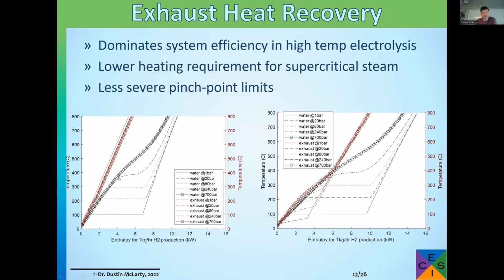The supply water is in the black lines, and the return exhaust gas is the red, at different pressures. And you can see as you go to higher and higher pressure, you get to supercritical steam, you actually need less heat addition. So this difference at the top between the red exhaust and the black supply, that's how much supplemental heat you need to add to the system. So you get a benefit when you go to high pressure.